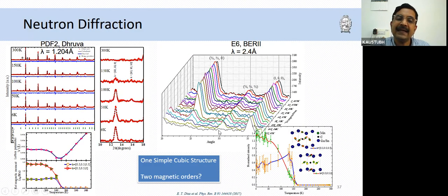No, no. I will show you the neutron diffraction data. You can see that around 155 Kelvin, this is the data at 155 Kelvin. Below 155 Kelvin, there are two magnetic orders. This is half of 0, which is like that of manganese 3 tin carbon. This is half of half, which is like that of manganese 3 gallium carbon. And the EXAFS also shows the same thing, that there are clusters which are rich in gallium and clusters which are rich in tin. And we say therefore that in the gallium rich regions, the ordering is as per half of half, and in the tin rich regions, it is as per half of 0.